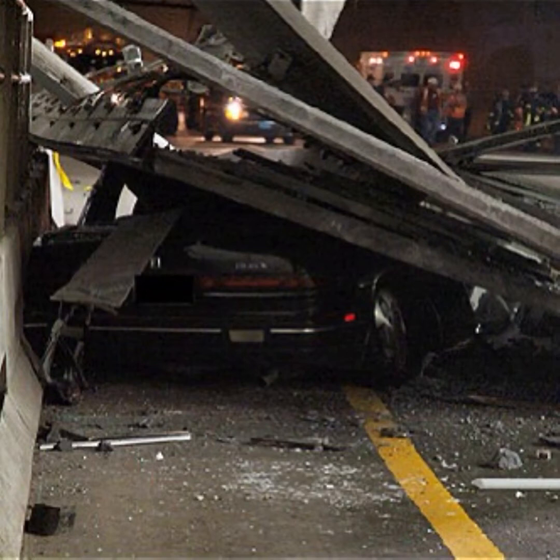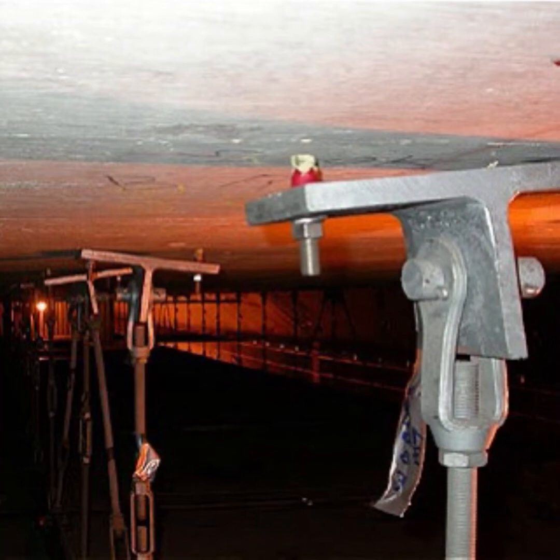The investigators also tested standard set epoxy under the same conditions and found that in the 82-day test under a 2,000-pound load, standard set did creep at about 1/10 of the rate of fast set, and it did so in a flat, linear increment. The fast set during that time exhibited a nonlinear, increasing rate of creep after just 55 days. So let's talk about the epoxy.